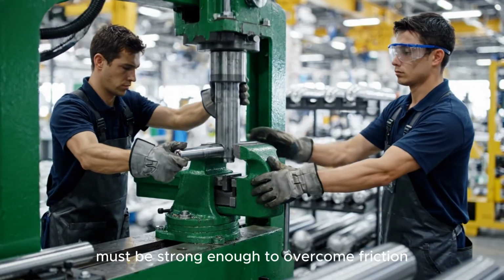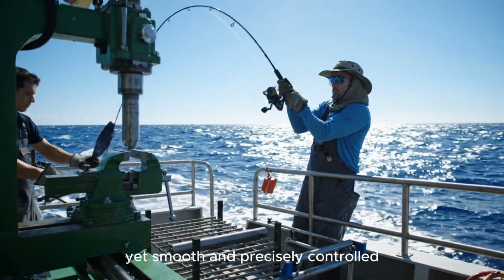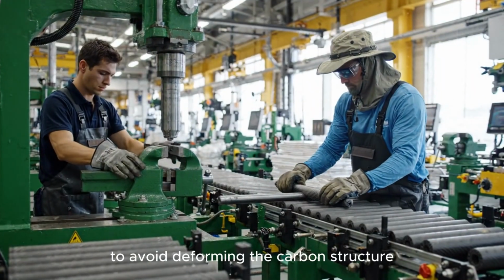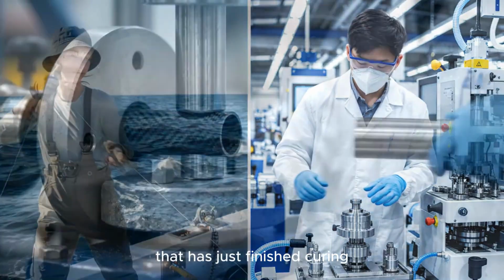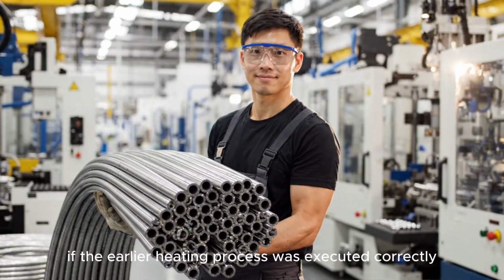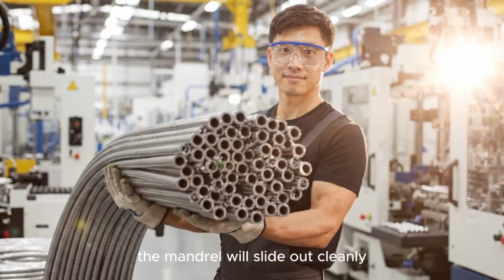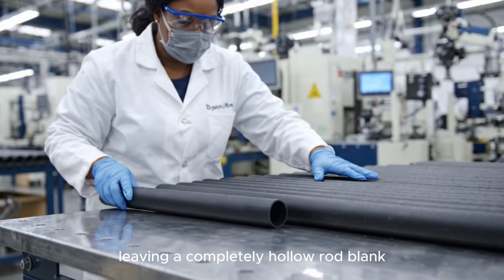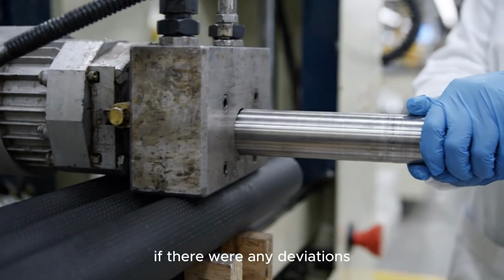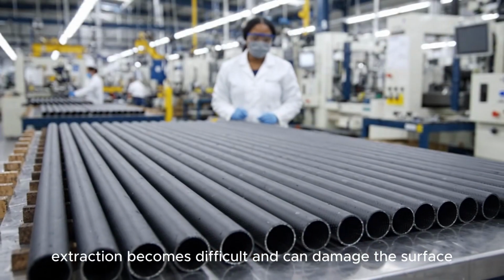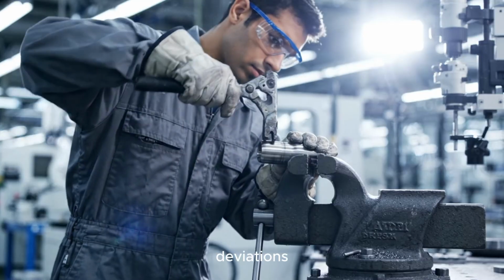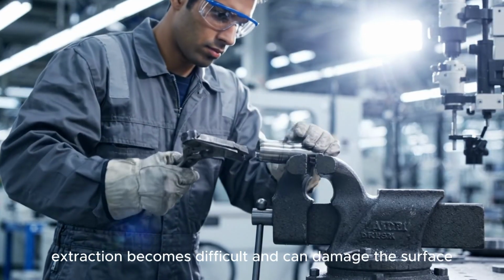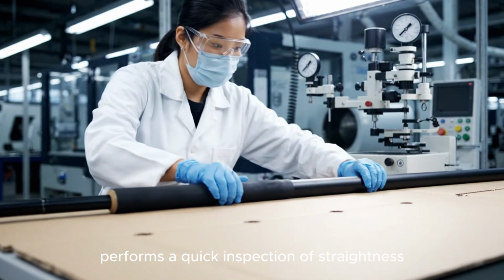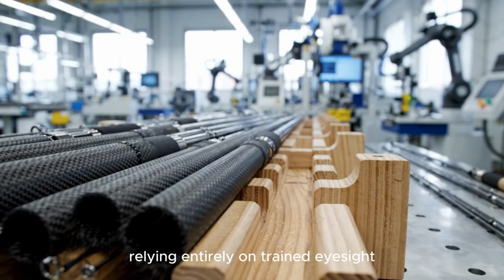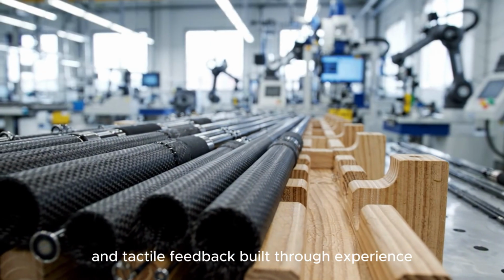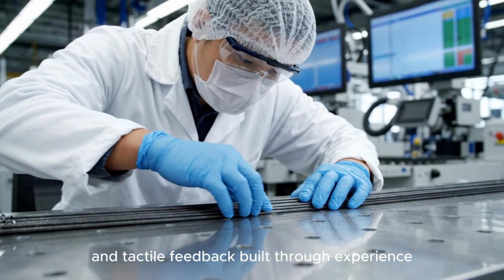The pulling force must be strong enough to overcome friction, yet smooth and precisely controlled to avoid deforming the carbon structure that has just finished curing. If the earlier heating process was executed correctly, the mandrel will slide out cleanly, leaving a completely hollow rod blank. If there were any deviations, extraction becomes difficult and can damage the surface. At this point, the technician performs a quick inspection of straightness and uniformity, relying entirely on trained eyesight and tactile feedback built through experience.